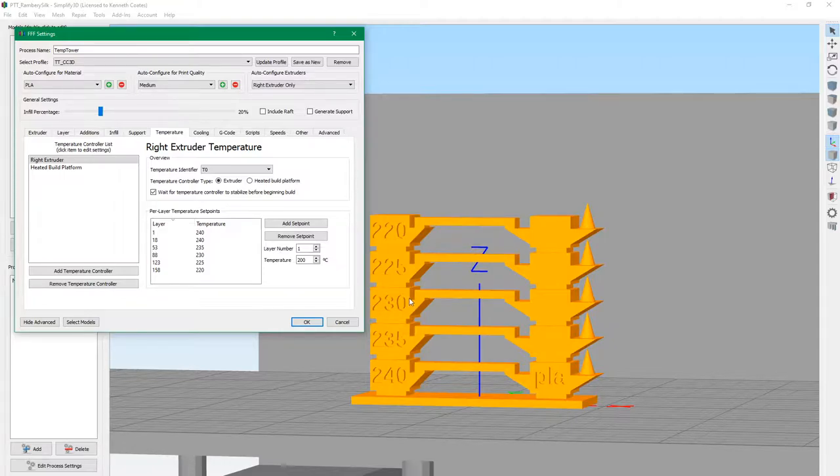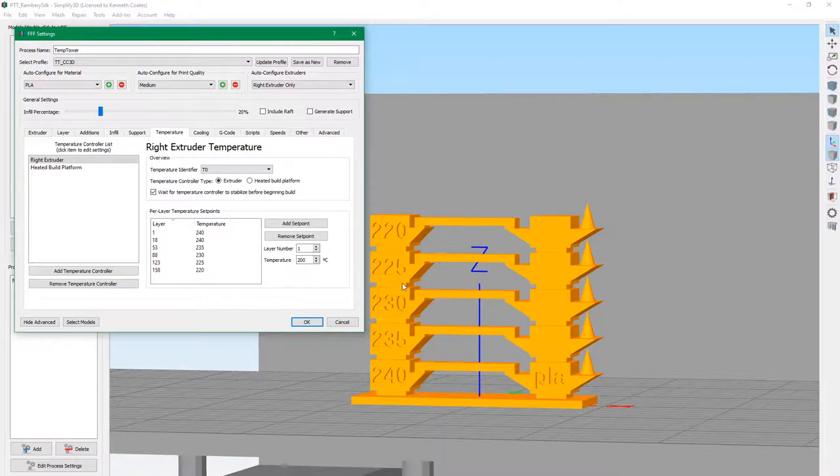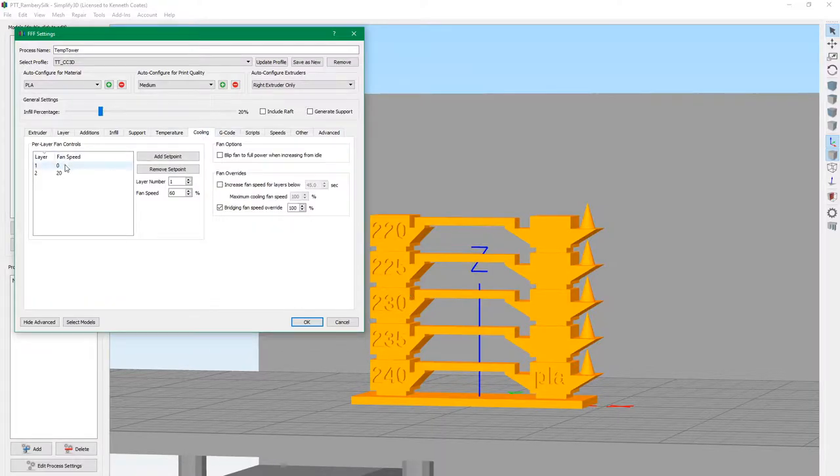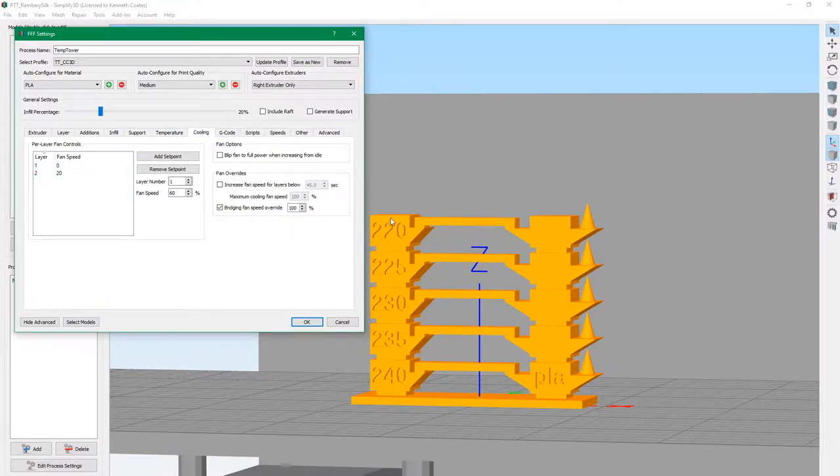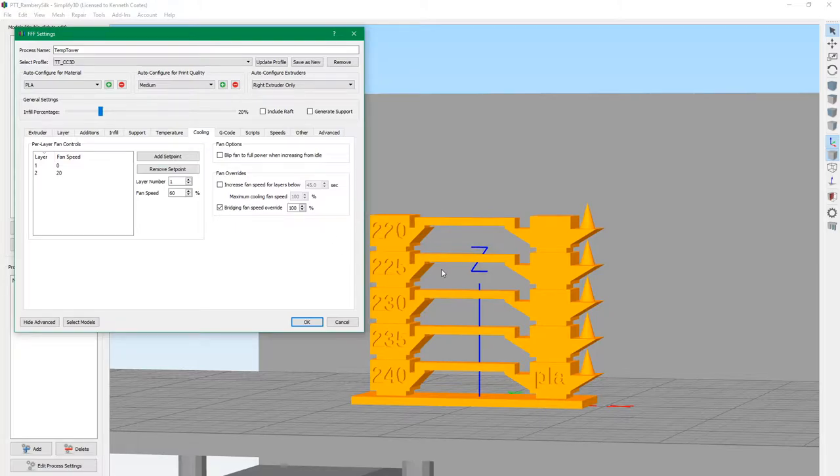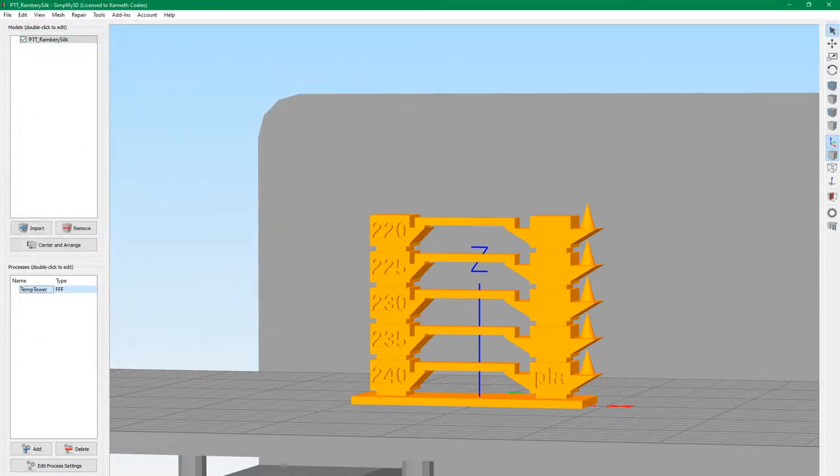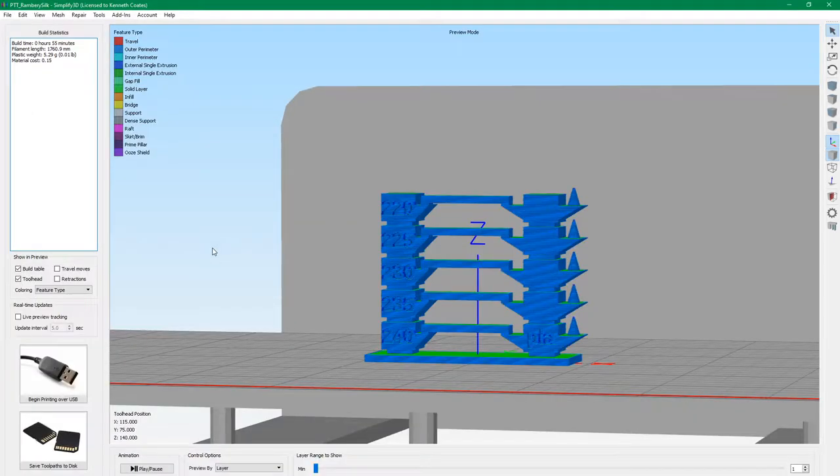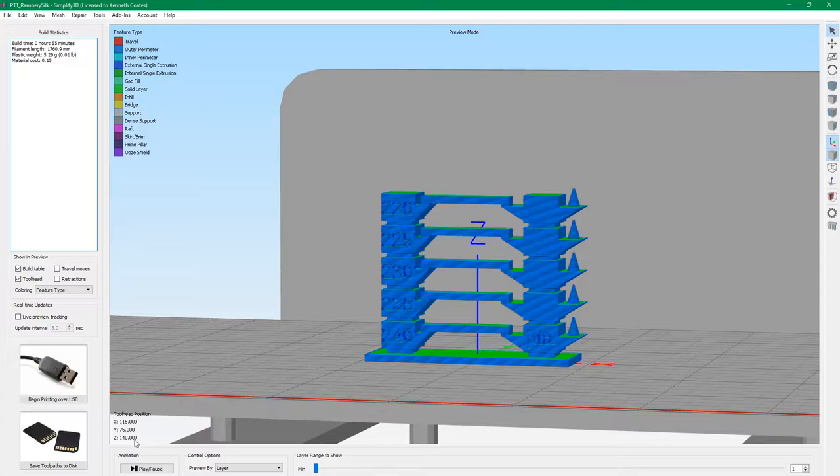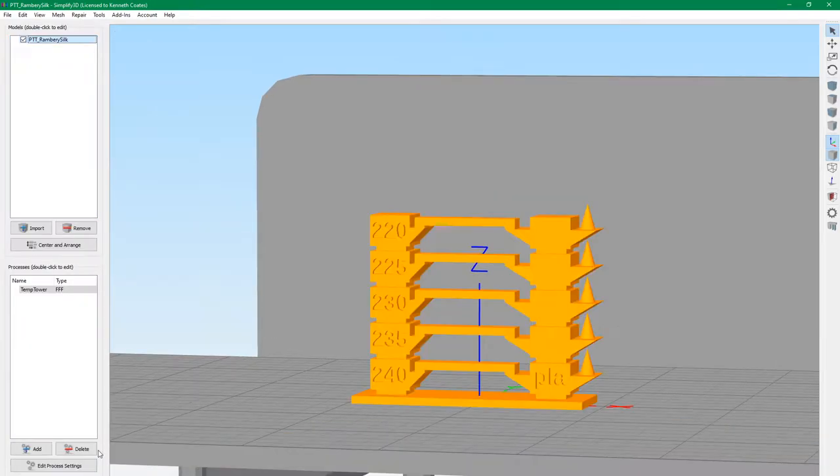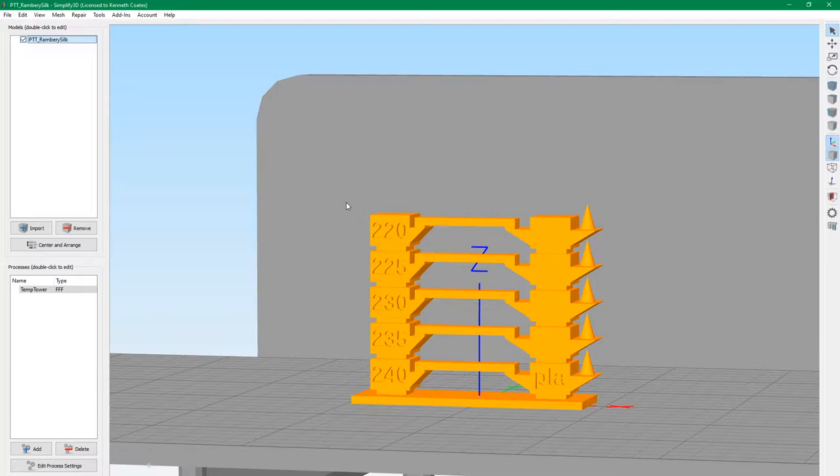Here we're mostly printing at 230 because when the temperatures are cold, the extruder can't actually maintain the setpoint at 230. It's maybe 3, 4, or 5 degrees colder, especially once you put some cooling on. Even 20% fan is going to lower the temperature significantly from what your setpoint is. This is going to take about 55 minutes, so that's not too bad.